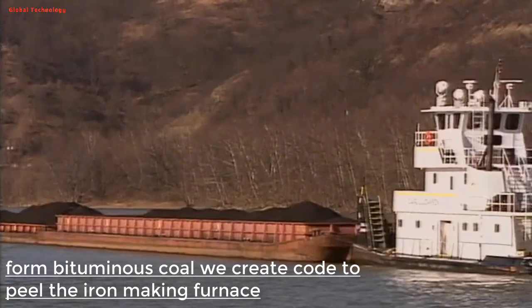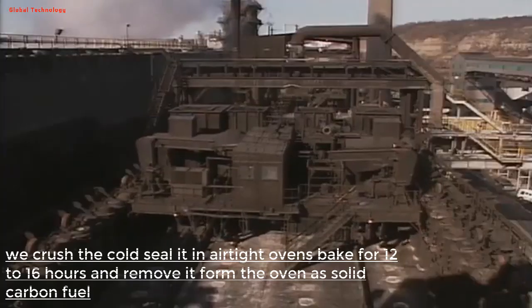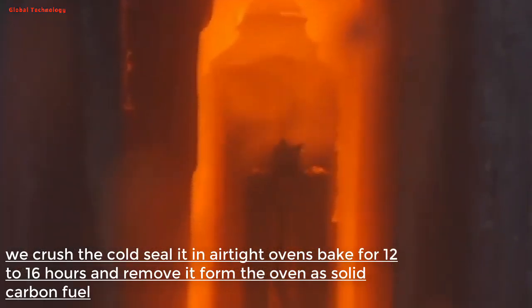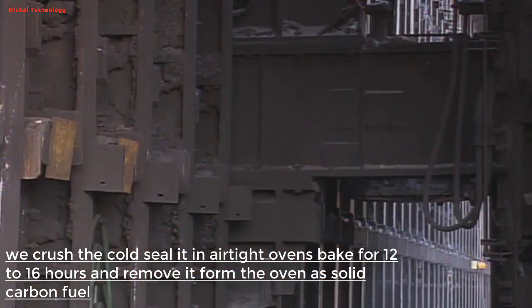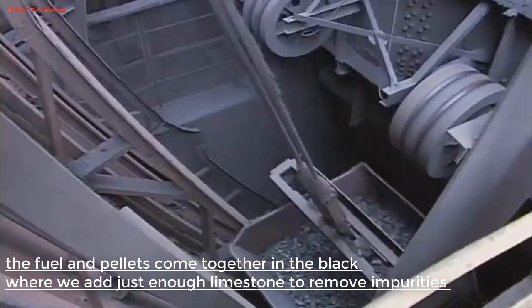From bituminous coal, we create coke to fuel the iron-making furnace. We crush the coal and seal it in airtight ovens, bake it for 12 to 16 hours, and remove it from the oven as solid carbon fuel. The fuel and pellets come together in the furnace, where we add just enough limestone to